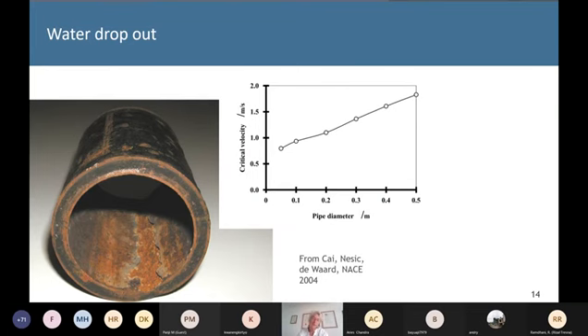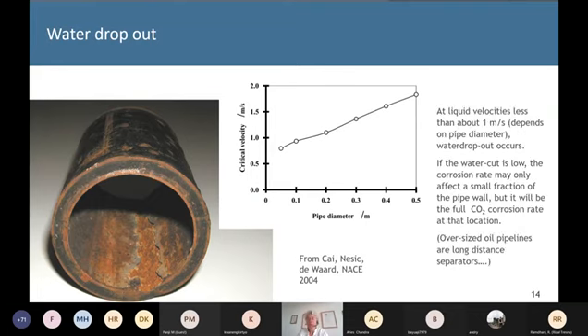That question of water dropout is also affected by pipe diameter. On the left, we've got a classic example of a line carrying oil, and you can see the groove in the bottom of the line that's been caused by the water dropping out. Because notwithstanding the previous equation I showed you, fundamentally there's a certain velocity at which even the smallest amount of water will eventually separate out from an emulsion. And in the typical diameters that we're mostly dealing with, around 0.2 to 0.3 of a metre, we're about 1 metre a second, but there is a variation with pipe diameter about this dropout velocity.